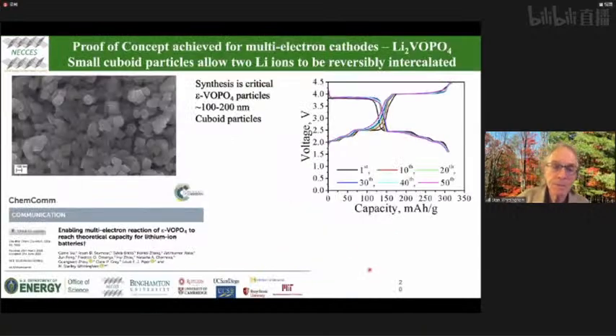So what does this material look like? They're little cuboids, about 100 to 200 nanometers in size, extremely uniform. What we do is, because this is a phosphate and therefore a very good electronic insulator, we have to make it a conductor. So we mix this with graphene. It's much more effective than carbon black. And you can see the electrochemistry on the right-hand side here.